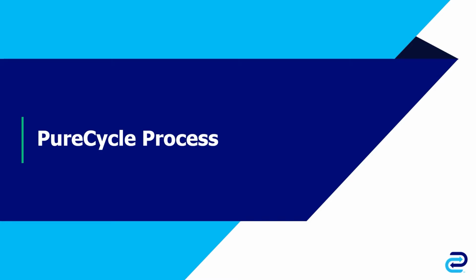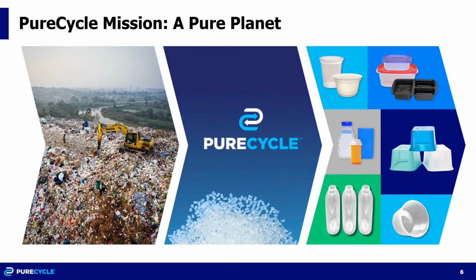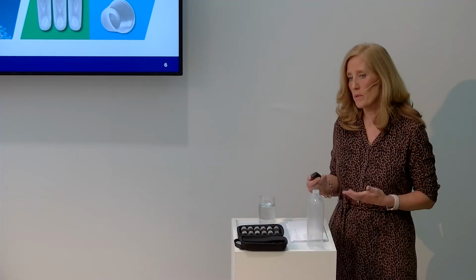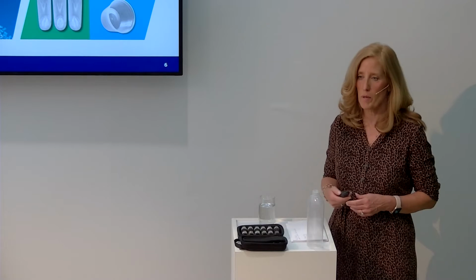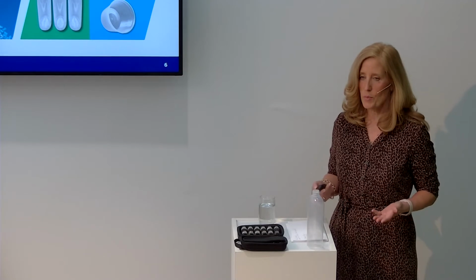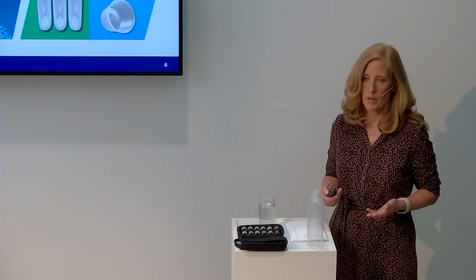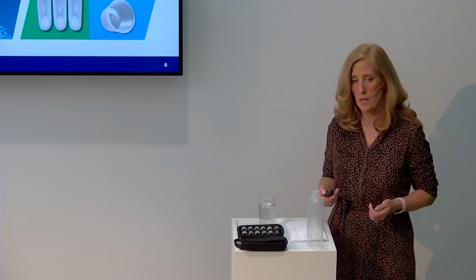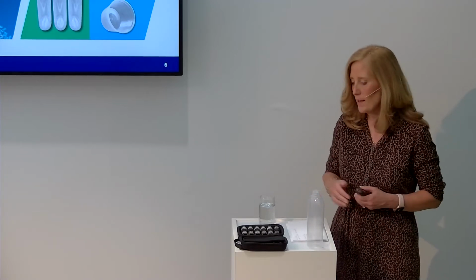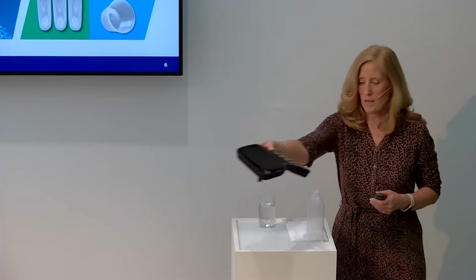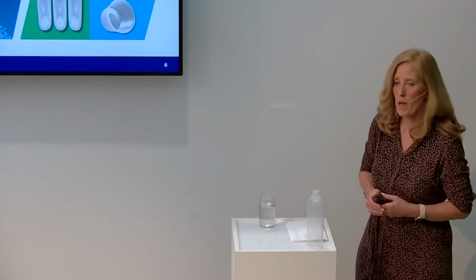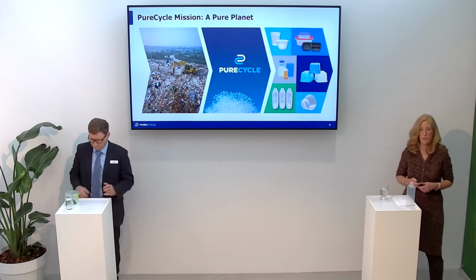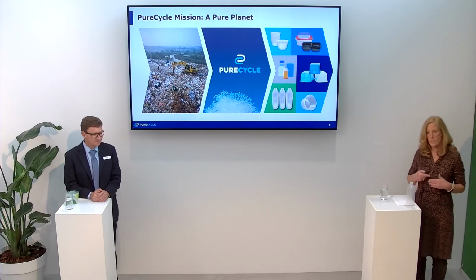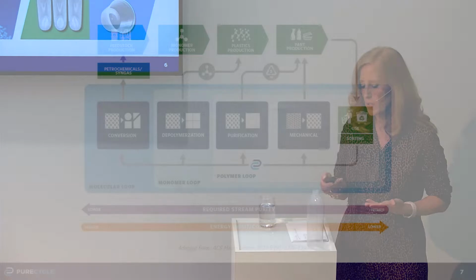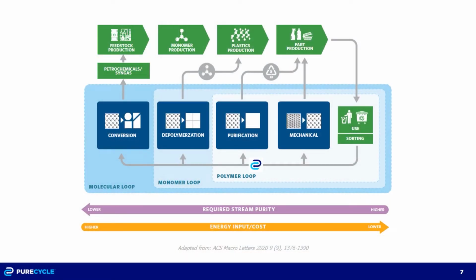So we're all here because we have a plastics crisis and we have a consumption of using too much carbon. So we need to bring solutions to both the plastics and also the amount of carbon consumed to make plastics. And so PureCycle is bringing a new technology, a new innovation into the market, commercializing dissolution technology where we purify polypropylene. I've brought samples to pass around of different medias of scrap polypropylene, from carpet to serviceware to curbside, where we've dissolved the polypropylene and filtered it and cleaned it to look like virgin material.